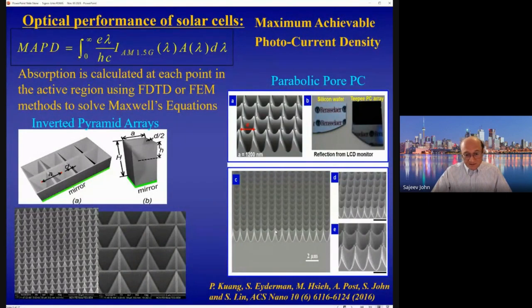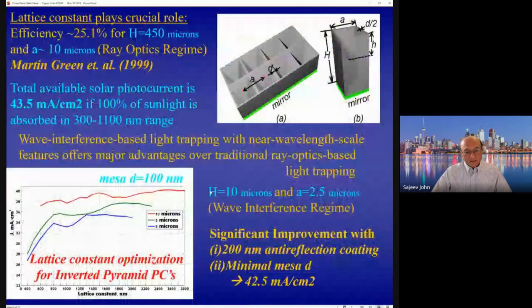The lattice spacing here is about 1.2 microns. In this picture, the lattice spacing between inverted pyramids is about 2.5 microns. So the use of inverted pyramids actually has a pretty long history, going back to one of the early world record solar cells, which was created by Martin Green's group in Australia nearly 24 years ago.